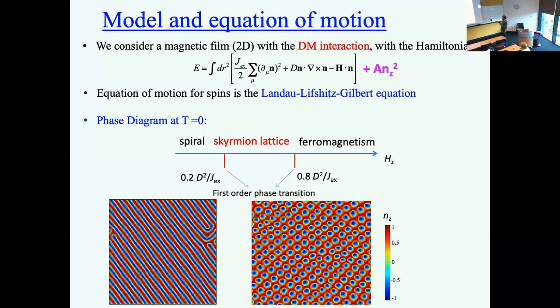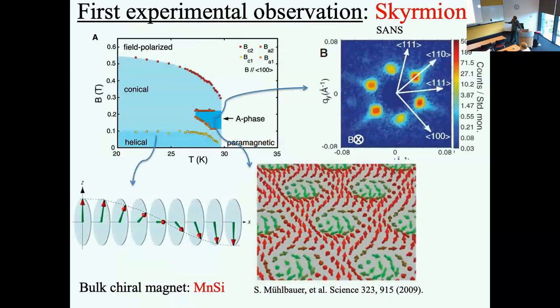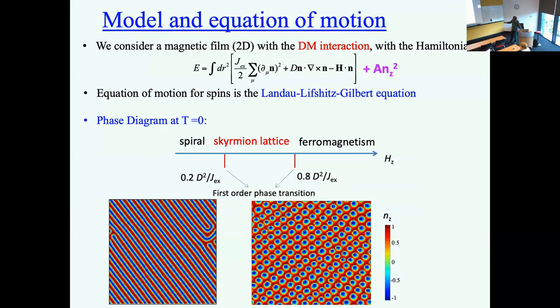So suppose I look at the simple phase diagram of this thing. I change D over J in some fashion. So you get the spiral phase as you saw in the previous diagram. And then at large magnetic fields, you see ferromagnetism. In between, you do see a lattice of skyrmions, a triangular lattice of skyrmions. So the simple model, the nonlinear sigma model, or gradient of, okay, let's call it symmetric exchange, antisymmetric exchange, Zeeman, and anisotropy. Now let's ask the following question. I want to have everything as it is, and change the anisotropy.